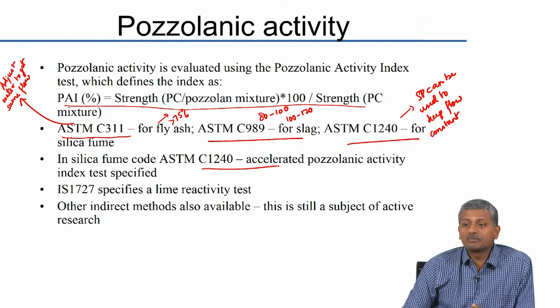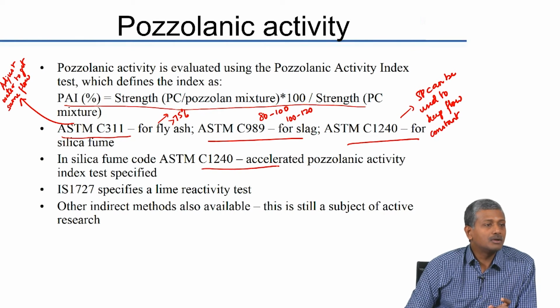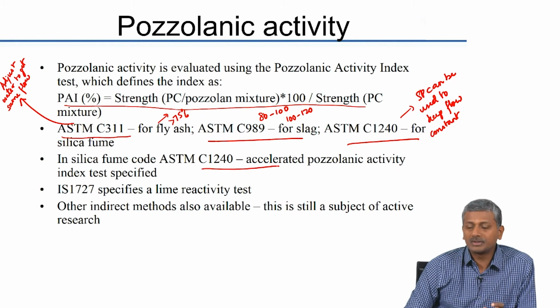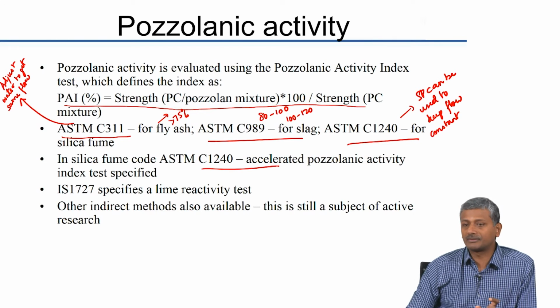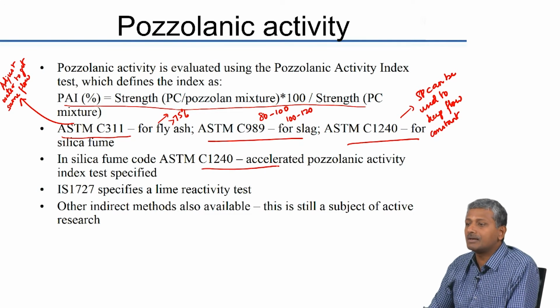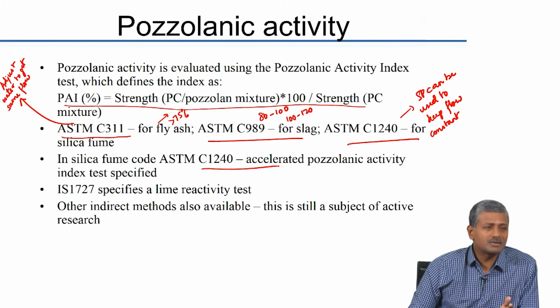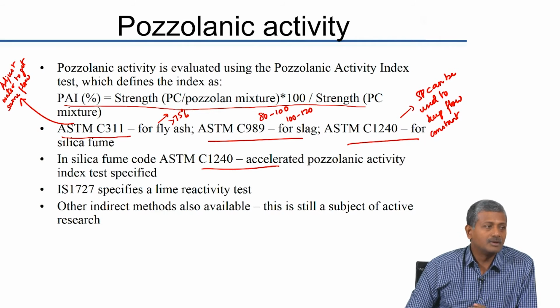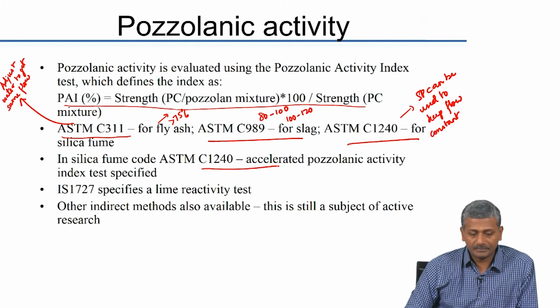And in the silica fume system, it is an accelerated pozzolanic activity test, where you are actually subjecting your mortar to a high temperature during the setting and hardening phase. Because of that, the strength gain rate is much faster, and I think you can get the result in about 7 to 8 days in this case. In the fly ash system, you have to wait the regular 28 days before you can get the result.